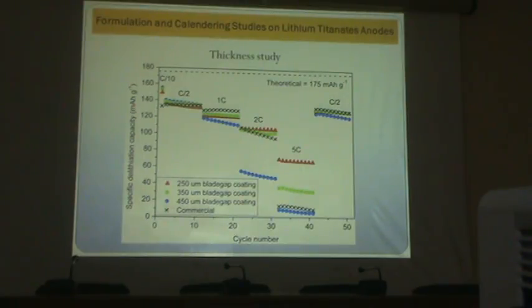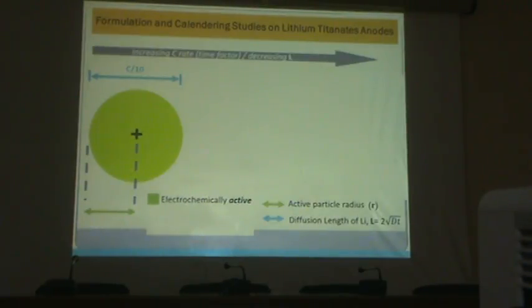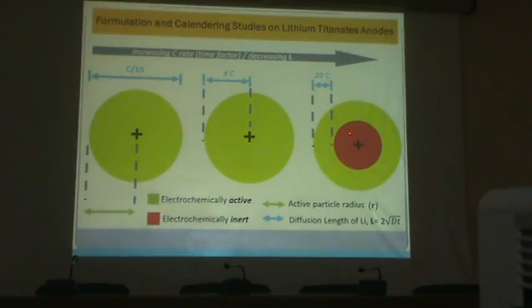Okay, so which is kind of expected because we thought literature is available, standard literature. When you are charging and discharging at a slow rate, the whole lithium titanate material is available. But when you go at a very fast rate, the availability, or rather the diffusion time, goes down. So that's why you see that the thinner the electrode, the better it is. But actually you cannot do that in practice. In practice you have to make an electrode sufficiently thick so that you can pack more and more anode material. That's your goal.